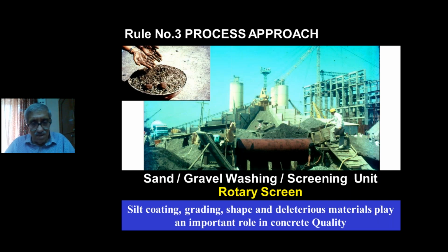We had to insist on the contractor to wash this coating so that clean aggregate goes into the batching mixing plant. With great difficulty, we convinced the agency to do it. Otherwise, we had to levy penalty on him for producing substandard concrete from a very state-of-the-art batching plant.